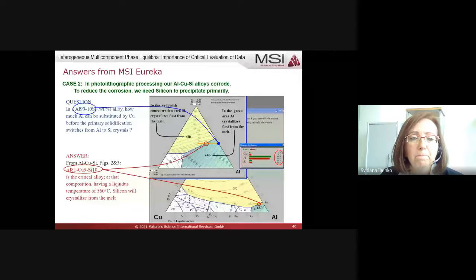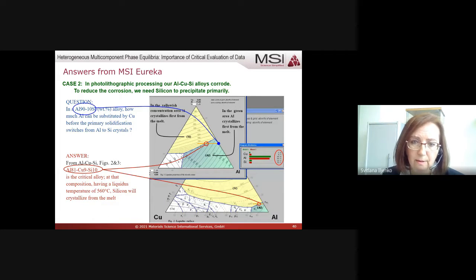Another example, in photolithographic processing, aluminum copper silicon alloy corrodes. It corrodes because aluminum is precipitating, and to avoid the corrosion, they would like to make it so that the silicon precipitates primarily. And the answer is also on the phase diagram. So one should check actually how much aluminium can be substituted by copper before the primary solidification switches from aluminium to silicon. So the answer is also here.